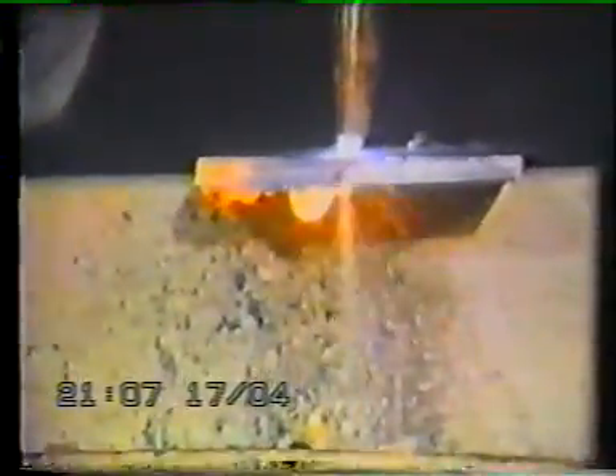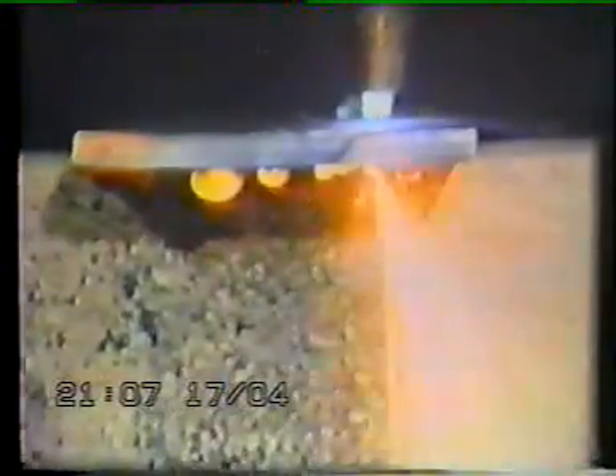Hold the handle in one hand for a firm control of the cutting oxygen lever. The other hand should be used to steady the torch. A comfortable but steady grip is essential for accurate cutting. Hold the torch perpendicular to the work. The inner cones of the flame should be just slightly above the cutting surface. Wait until this spot is red hot. Then slowly press down the cutting oxygen lever all the way. A shower of sparks from under the metal indicates that the cutting has started. Apply the same pressure during the entire cut. If properly cut, the waste will drop off and the edge will be clean.